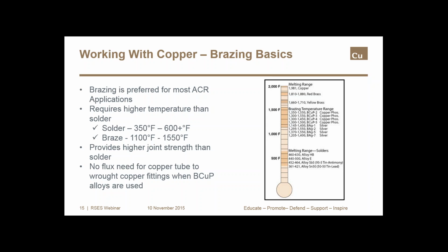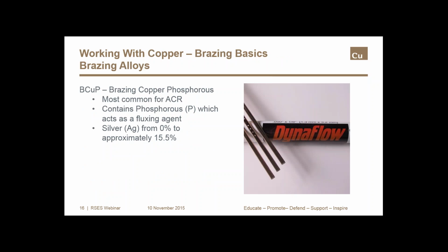And when brazing copper tube to wrought copper fittings, it does not require flux because the phosphorus in the filler metal does that job. However, when other metals are brazed, fluxes are typically required, and it's critical that the correct flux is used. Looking at filler metals, there's two basic types normally used in air conditioning and refrigeration applications. There is a brazing copper phosphorus, or BCuP series, and a brazing silver, or BAg series.